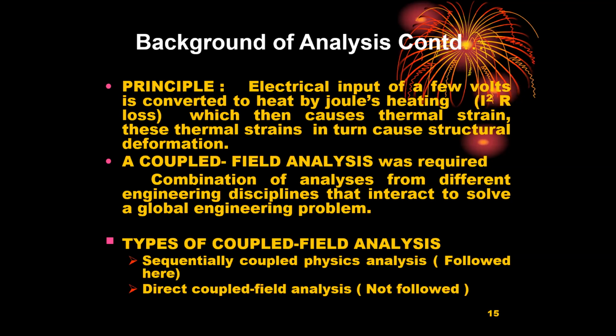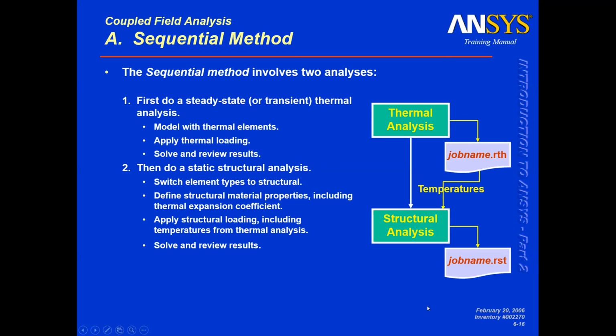So we had to do what's called a coupled field analysis, which combines the analysis from different engineering disciplines that interact to solve a global engineering problem. We had to do first in ANSYS an electrical to thermal analysis, and then a thermal to structural analysis, and then incorporate the influence of moisture through analytical tools, and then do a complete failure analysis modified to accommodate the influence of moisture at elevated temperatures or any temperatures up to the MOT and beyond. So we had to choose what's called a sequential method, as the direct coupled method analysis was not giving us precise results, as the whole process is sequential.